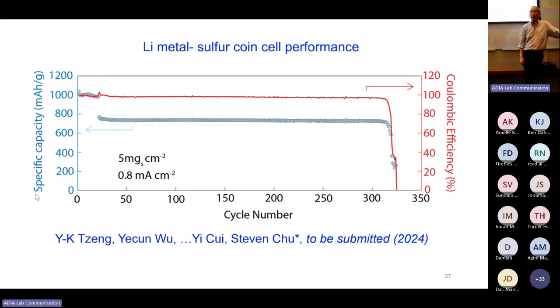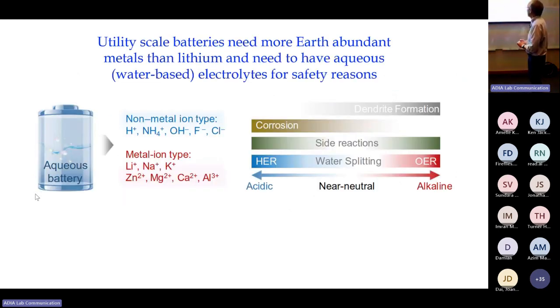Similar is true of aqueous batteries. You want aqueous batteries for utility scale because they don't catch fire. And there's a problem with aqueous batteries. You can have any ions you want: sodium, potassium, zinc, manganese. It's not going to be lithium, but if you have it in an aqueous solution, you can begin to split water and make hydrogen or oxygen. So that means the battery has to work below 1.3 volts, which means instead of 3.5 to 4 volts, you're much lower in energy density.